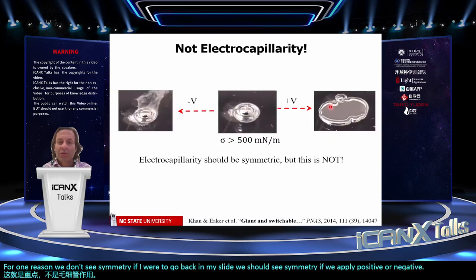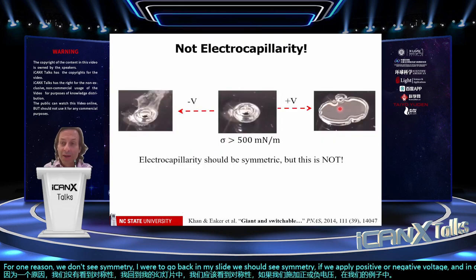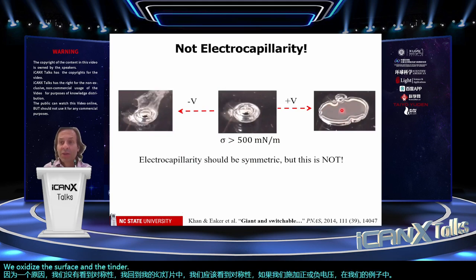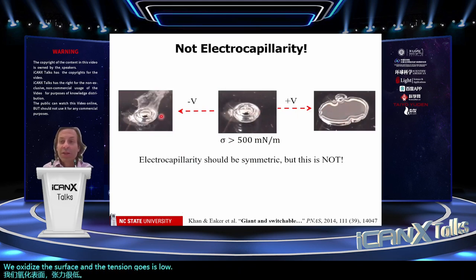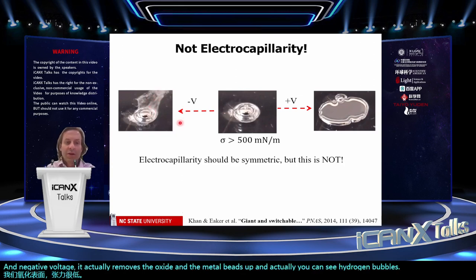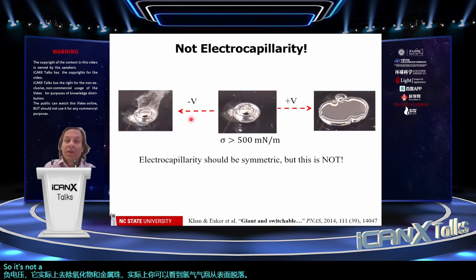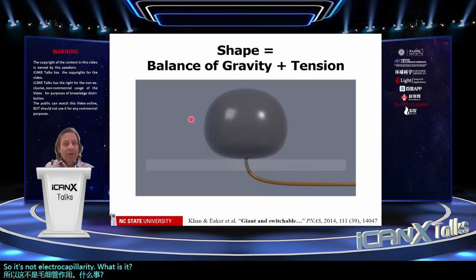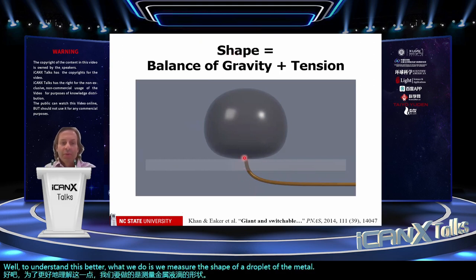And in our case, if we apply positive voltage, we oxidize the surface and the tension is low. And negative voltage, it actually removes the oxide and the metal beads up. And actually you can see hydrogen bubbles coming off the surface here. So it's not electrocapillarity. What is it? Well, to understand this better, what we do is we measure the shape of a droplet of the metal. And we apply a voltage using a very small wire, as shown here.